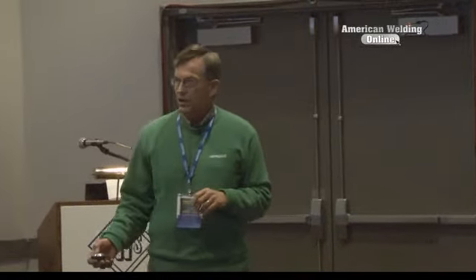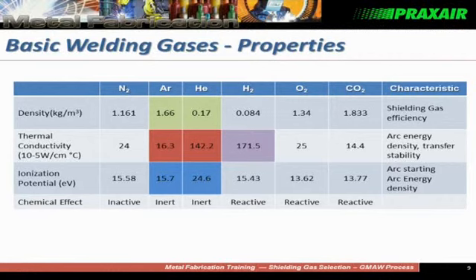Just to give you a little bit of background, I know people love numbers and tables like this, but just to highlight a couple of things. The reason why different gases are used in welding is because they have different properties. They have different effects on the welding process. Good example here is argon and helium. Why do we use argon or helium or hydrogen in some cases? And when we're talking about stainless steels and nickel, we can use some hydrogen because it doesn't have a negative effect on the properties of the weld. But one of the reasons here is the thermal conductivity of the gas, how much of the energy generated in the arc gets transmitted to the base material. This relates to fluidity, this relates to travel speed, this relates to actually controlling metal transfer.